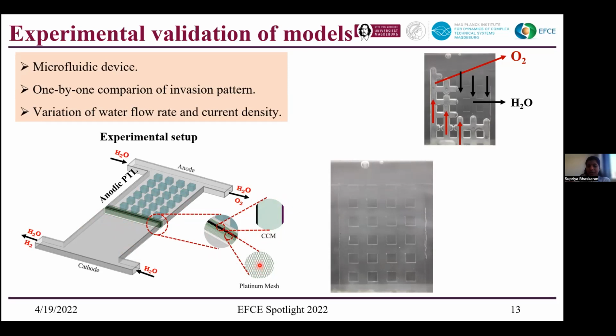And as a current collector, we have used a platinum mesh, which transfers the electrons, and the reaction occurs at the catalyst layer. And then we see the one-by-one comparison of the invasion pattern once we start the process, and how we can also study the variation of water flow rate and current density. So before showing the video, I would say what you can actually see in the video. You can see this transparent part, which would be the oxygen generated from the catalyst layer. And you also can see how the water, which is moving towards the flow, removes the oxygen out of the porous transport layer.